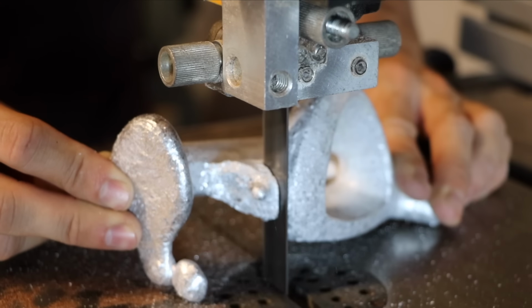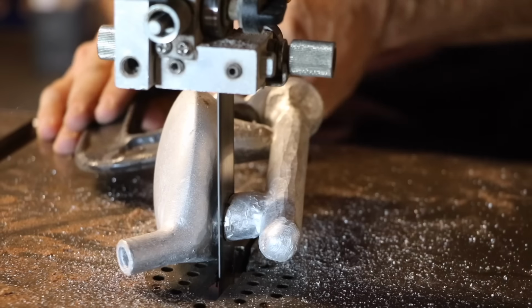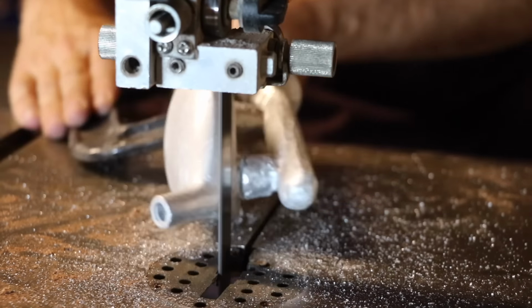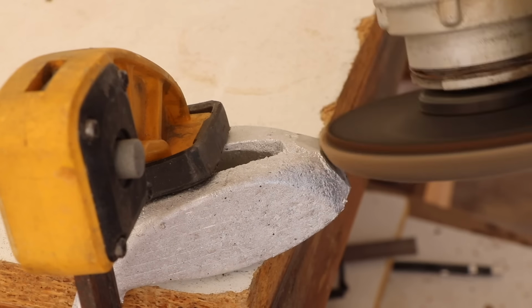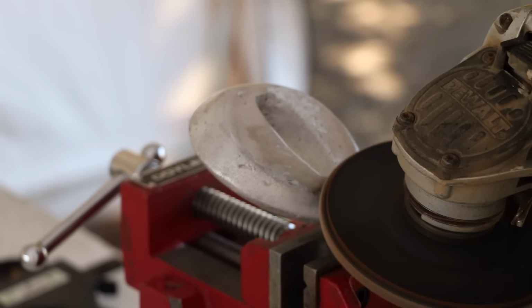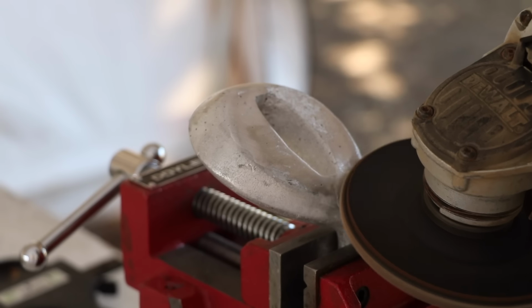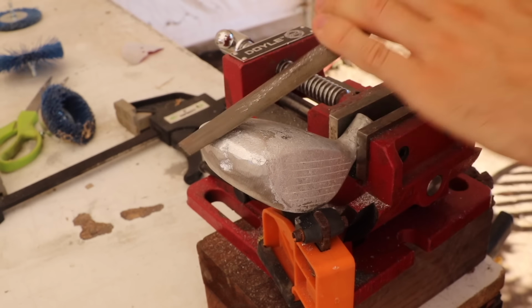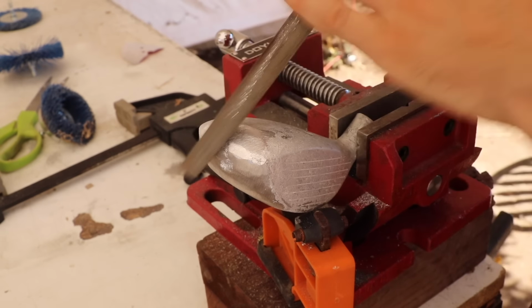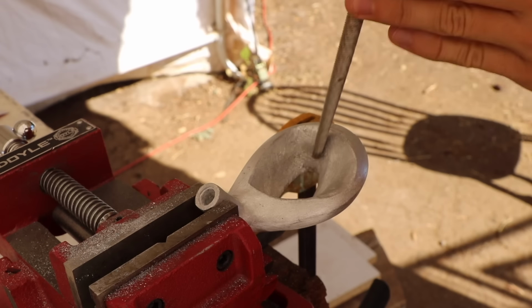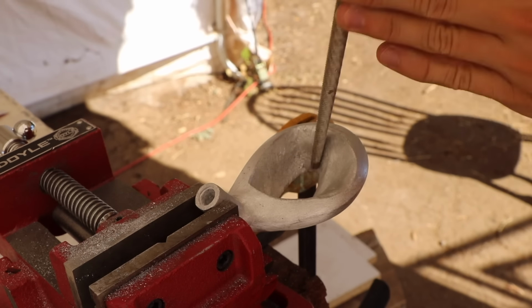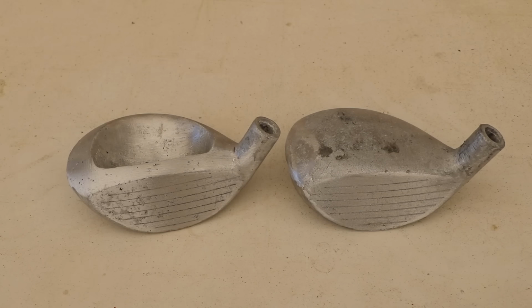Fortunately, and to our surprise, we got 2 usable castings on the first go, which is a big step in the right direction for us. They're not perfect, but they're good enough for us to use. The solid aluminum 5-wood has some shrinkage on the toe, so we'll have to reshape the toe slightly, which shouldn't really be a huge deal since it was already going to come out significantly overweight anyways. And besides that, it's just some general cleanup on these to get them ready for the heat treatment.